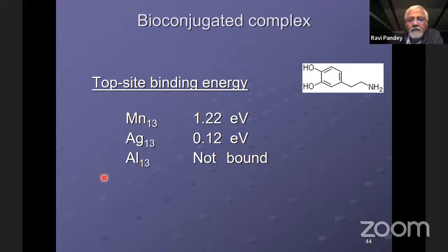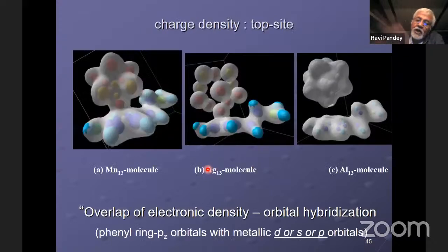From there, you can calculate the binding energy of Mn13 with dopamine, which comes out to about 1 eV for manganese 13. Silver, you can see, is a big difference. It is an order of magnitude lower than what we have for manganese, and aluminum is simply not bound at all. It doesn't like the dopamine molecule. So if you look at the so-called charge density at the interface, you can clearly see this overlap of electron density, what we call orbital hybridization, which is really preferred for this d-type manganese 13. And we have the dopamine carbon ring on the top side, so we have the pi electrons sitting on top. So pd hybridization is definitely preferred over silver, which is s-type, sp, or of course pp, as we know from chemistry 101, they don't like each other.